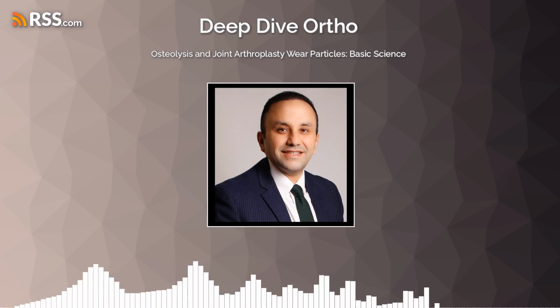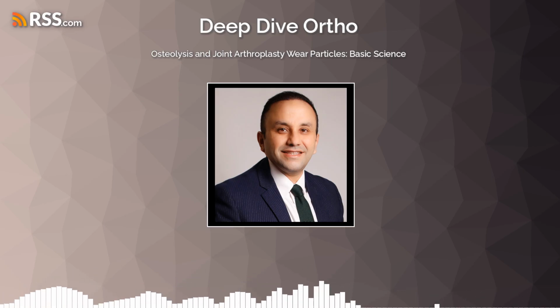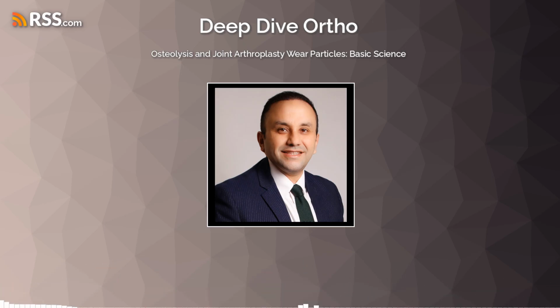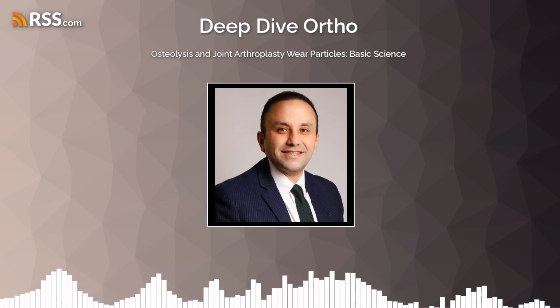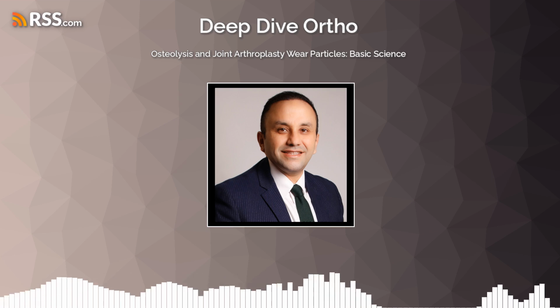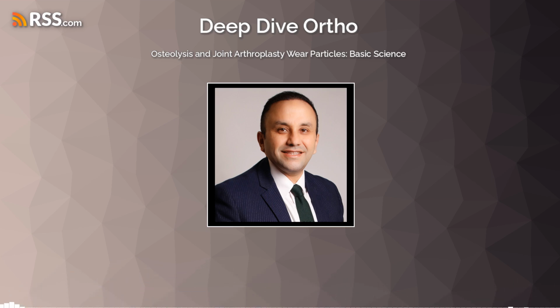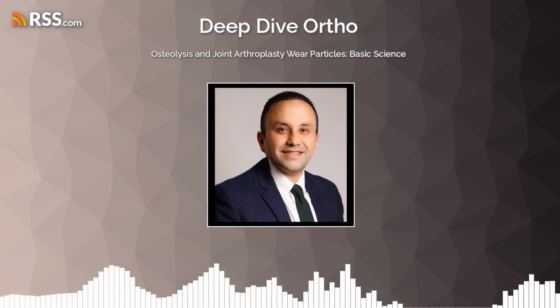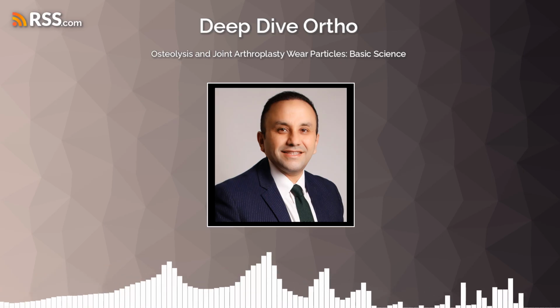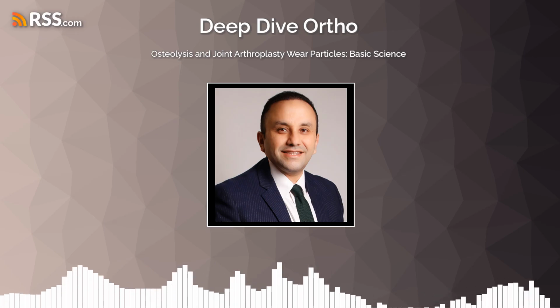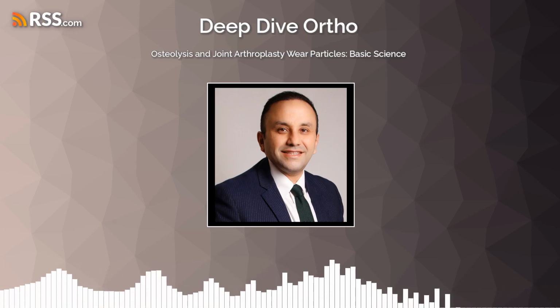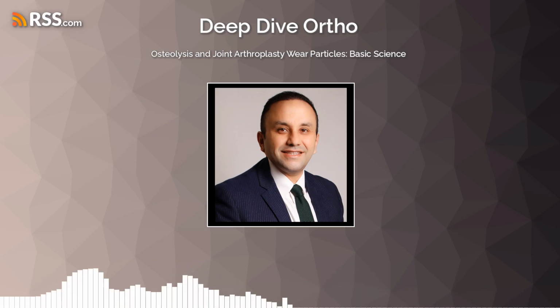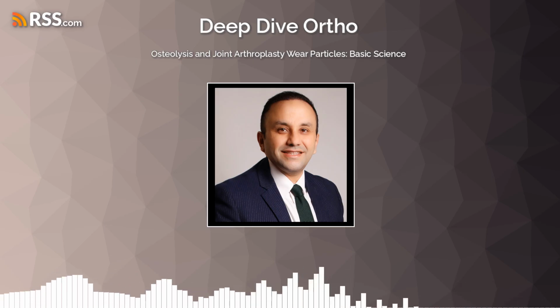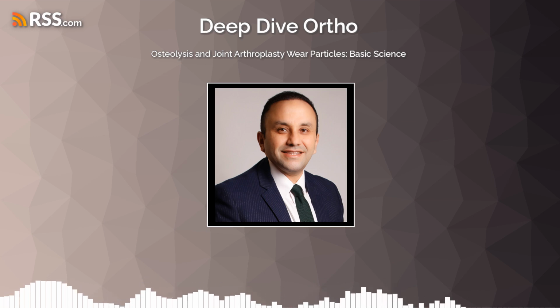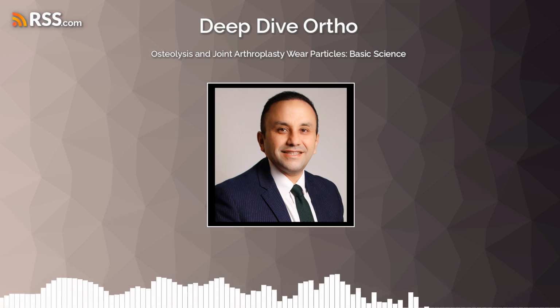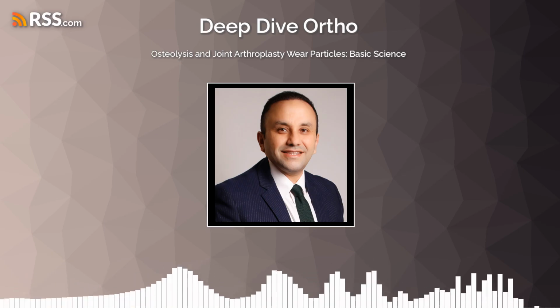Unfortunately, wear particles not only stimulate bone resorption by activating osteoclasts, but also actively interfere with bone formation. So they stop the repair process too. They actively hinder it. This dual negative impact is a crucial aspect of why osteolysis progresses so relentlessly and why the resulting bone defects become so challenging to manage during revision surgery. Studies, both in vitro, in lab cell cultures, and in vivo, in sophisticated animal models, have clearly shown that both metallic and polymeric particles inhibit the proliferation, differentiation, and overall function of crucial cells involved in bone regeneration. Which cells are affected? These include mesenchymal stem cells, which are the precursor cells that can become bone-forming cells, osteoprogenitor cells, which are more committed to becoming osteoblasts, and the osteoblasts themselves, the primary bone-forming cells responsible for laying down new bone matrix. Well, the whole production line for new bone is disrupted.